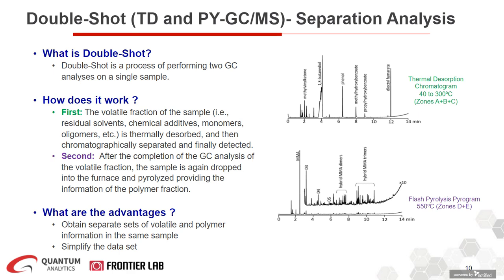One important point I want to make here is that the cup in a double shot mode comes down first for the thermal desorption, then goes back up to ambient temperature, so you're not exposing your sample to any heat in between your runs. Once the thermal desorption chromatogram is obtained, as you can see here in this example, the first chromatogram, and your furnace is ready for the second shot, which in this case was 550 C, the cup free falls again into the furnace for doing the flash pyrolysis.